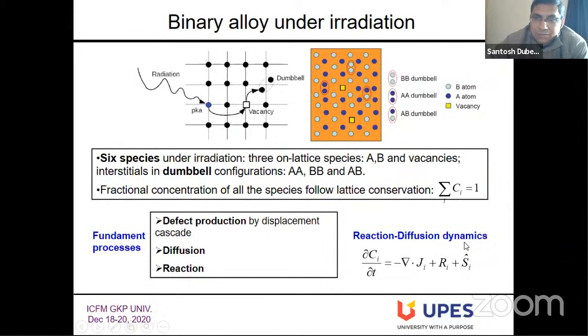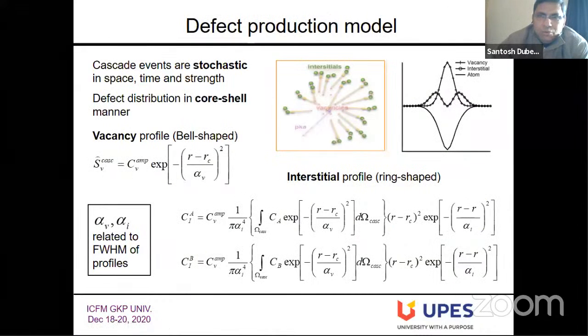And then at the end you have the source term, which drives the evolution of the concentrations. I won't go into detail, but I'll just tell you how I made the defect production model. Looking at the structure of this cascade, at the center you have vacancies surrounded by defects and interstitials. So to represent the interstitials, I use a dumbbell.